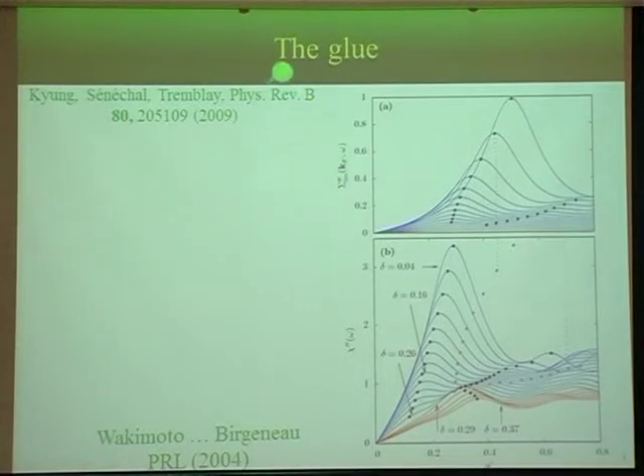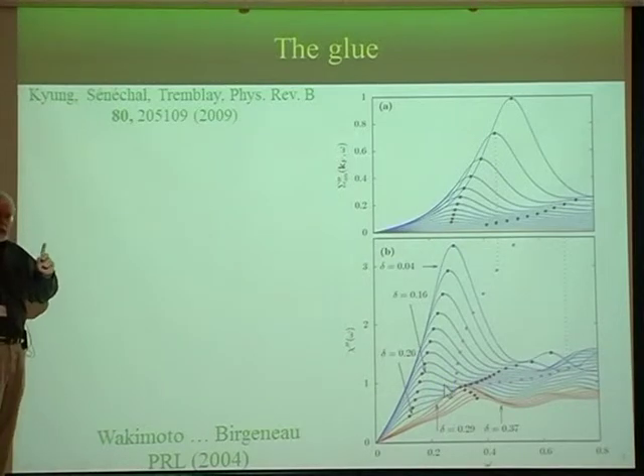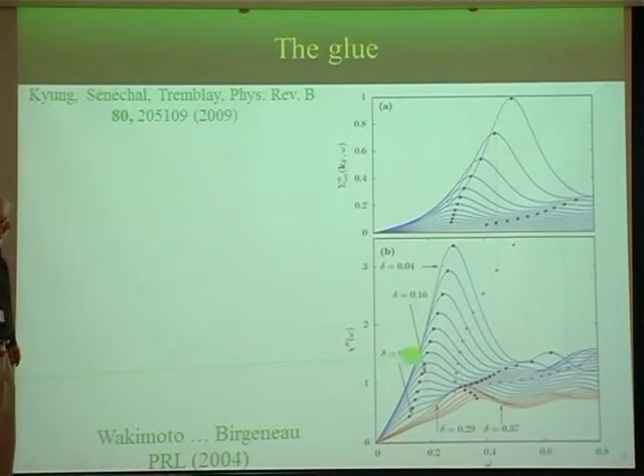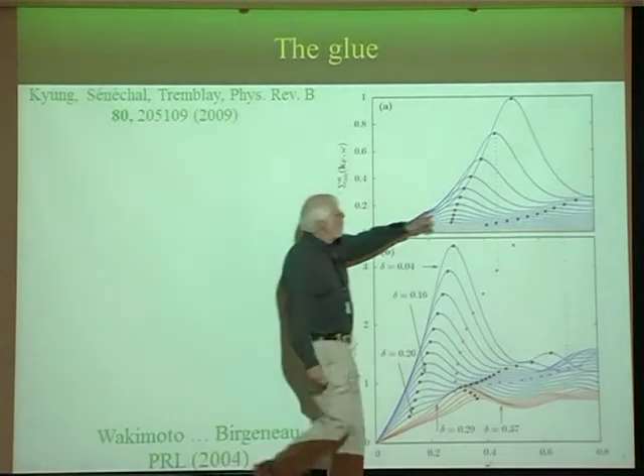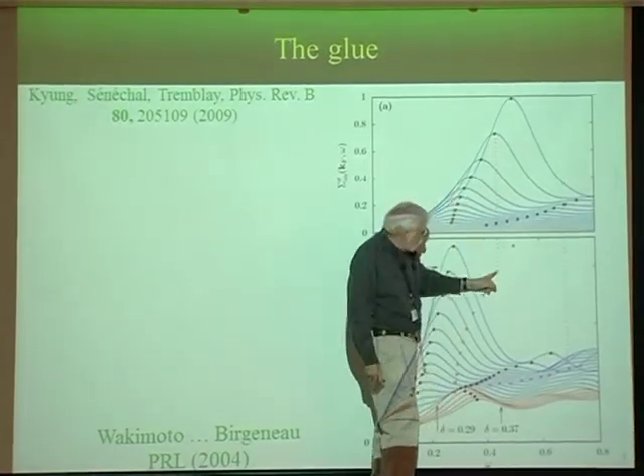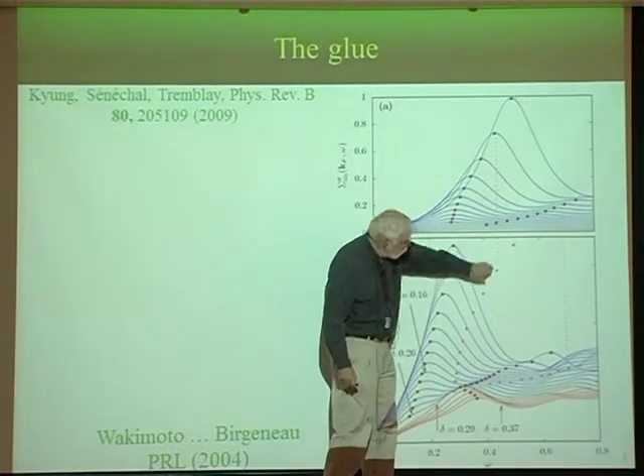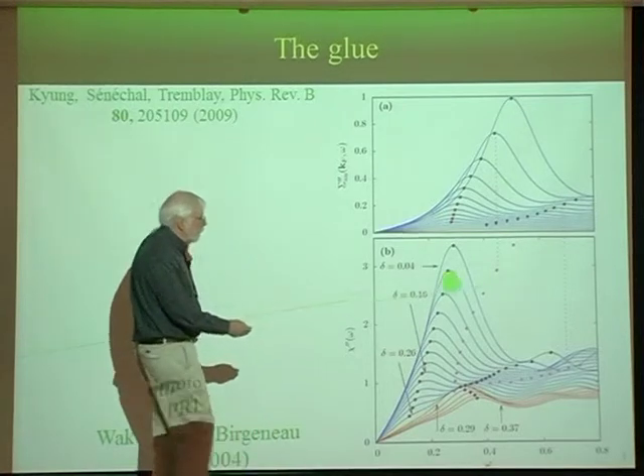So here is what we find for the glue in these cluster dynamical mean field calculations. I plot again the imaginary part of the self-energy as a function of frequency in units of hopping. Again, there are two bumps, and these are just different dopings. This is very close to half filling, and you go to the overdoped region this way. These are the corresponding curves for the single site spin susceptibility. As you see, there are two bumps also in this chi double prime. If you just take the maxima here and draw them as these purple dots, you see that they follow each other. The same for this other curve.